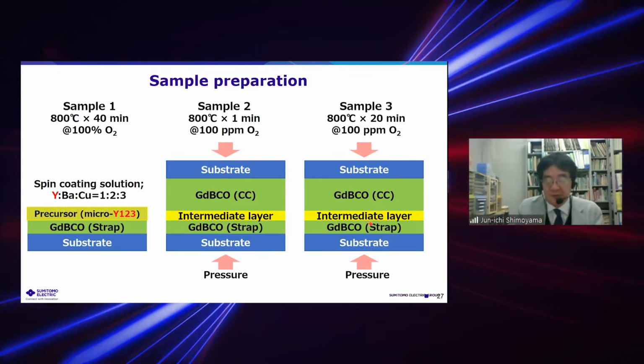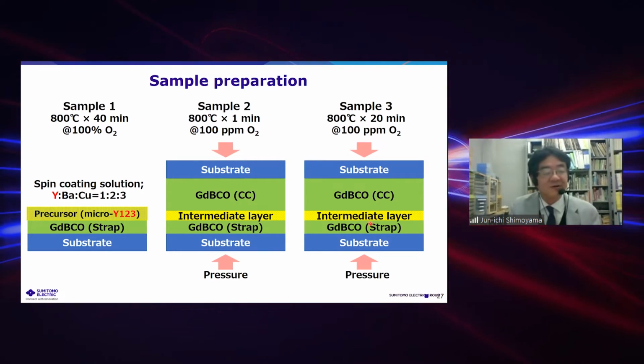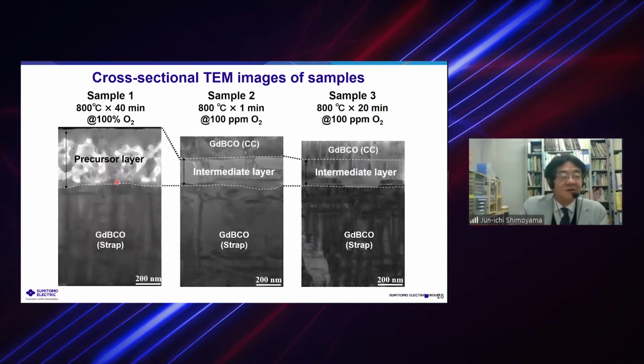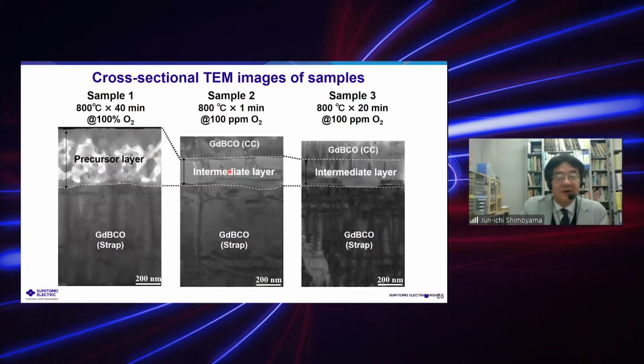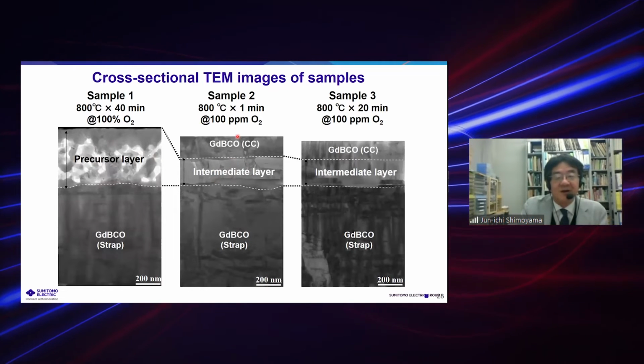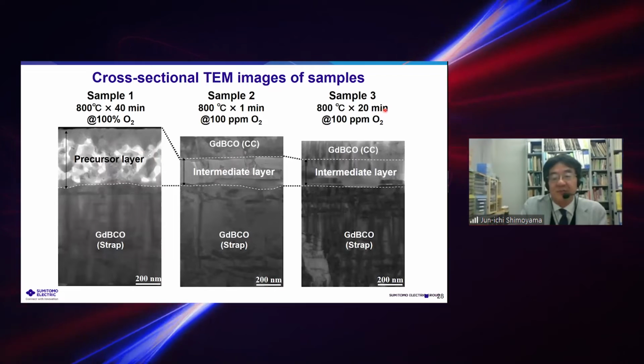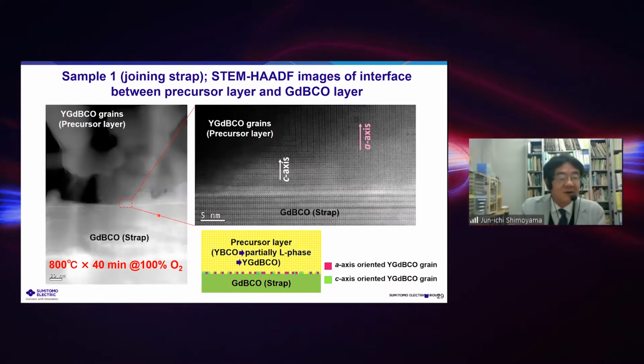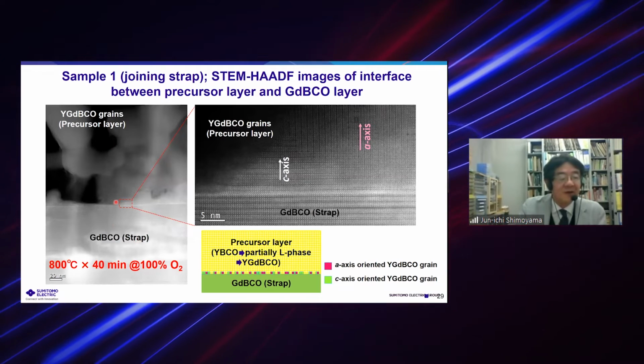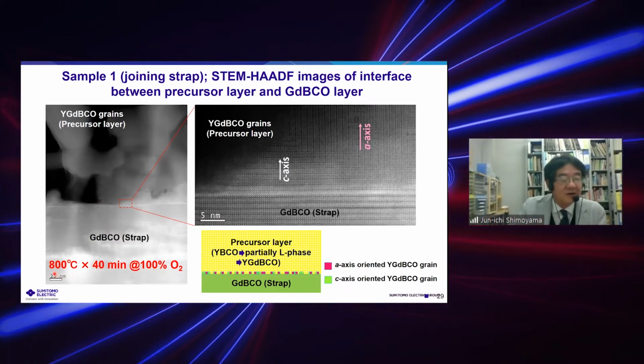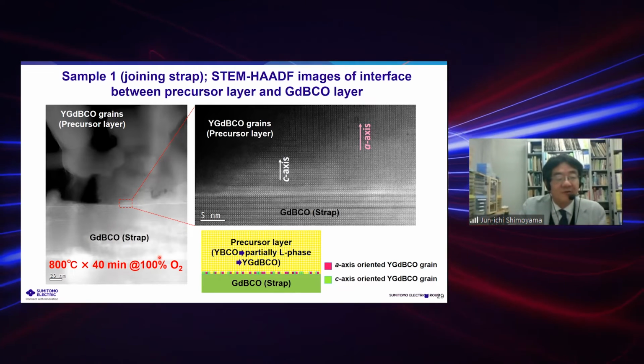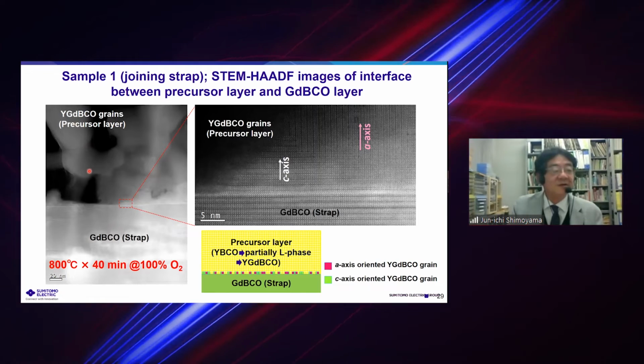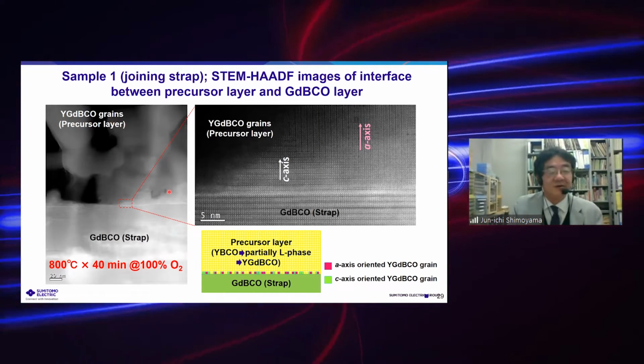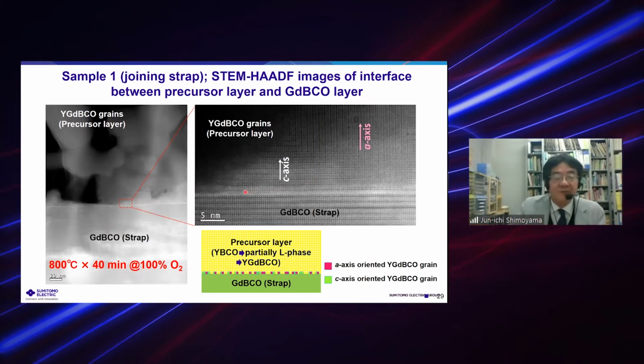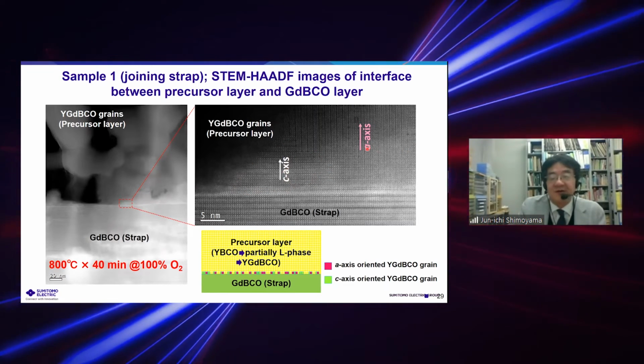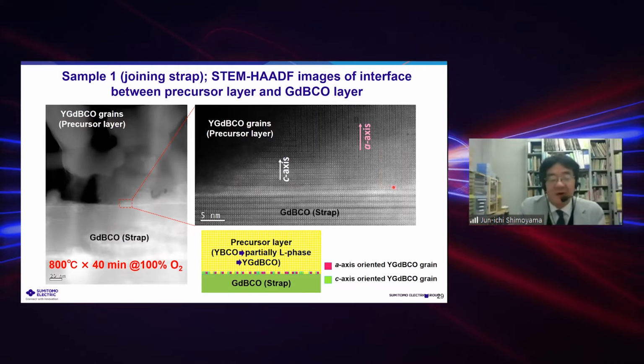The structure is almost the same, but let's see more precisely about this scheme. This is a precursor layer, a thick layer, which turns into a very dense and thin intermediate layer after heating at 800 degrees C for 1 minute or 20 minutes. If we look carefully at the interface between the strap and the precursor layer, this picture is taken for the sample heated at 800 degrees C for 40 minutes in pure oxygen. There are many small yttrium-123 grains here. But if you look here, very small regions composed of c-axis-oriented layers and a-axis-oriented layers were found at the interface.